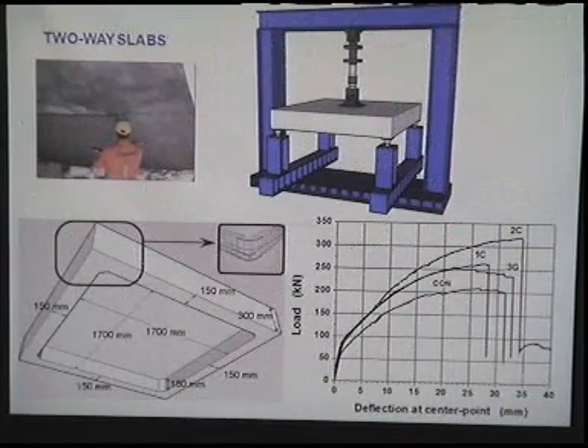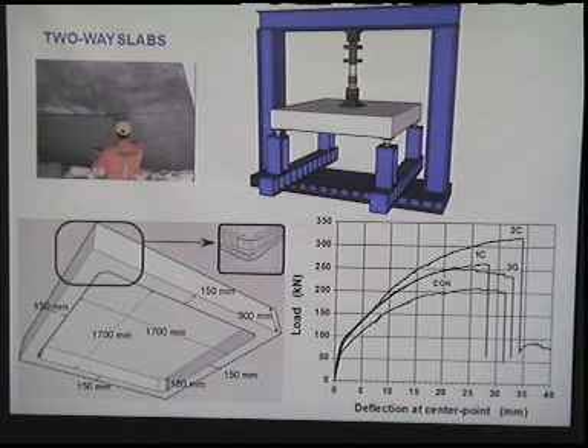But it is certainly a very good idea when we deal with two-way slabs, with slabs in buildings. Given the fact that we have fibers in two directions in those textiles, we can use those fibers to carry tension forces, tension stresses in two-way slabs. We tested a number of those in our laboratory. You see, for example, the load versus deflection curve of a slab without any strengthening. It is this curve here at the bottom.